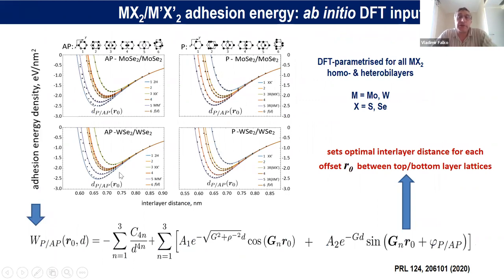What is shown here is the calculation using density functional theory of the interlayer distance dependence of the crystal energy for various ways to put one monolayer on top of another. We did this analysis for all TMDs, and also we looked at the heterostructures, forcefully making their lattice constants equal, and we checked that it doesn't matter whether we fit the lattice constant, for example, of tungsten diselenide to molybdenum diselenide. The results for what we need for the analysis of the structures at the mesoscale coincide.